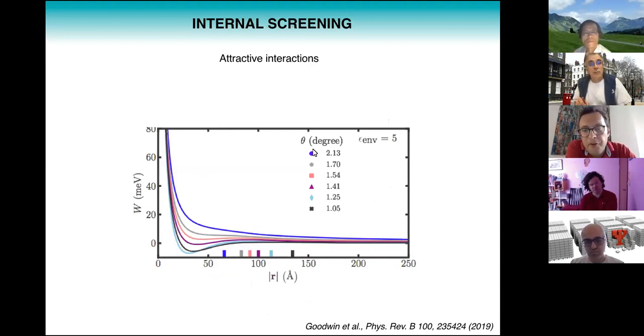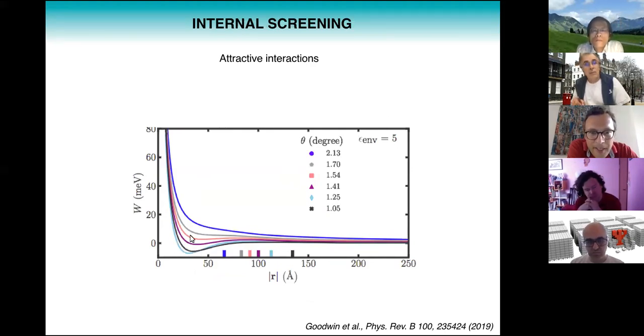What you see very far from the magic angle, let's see, the blue curve, basically says we have a repulsive interaction, as we would expect between electrons. Now, as we go closer and closer to the magic angle, at some point, around 1.4 degrees, the effective interaction actually becomes attractive between 2 electrons. And so this is a purely electronic interaction. It's not spin mediated, it's basically a polarization effect.